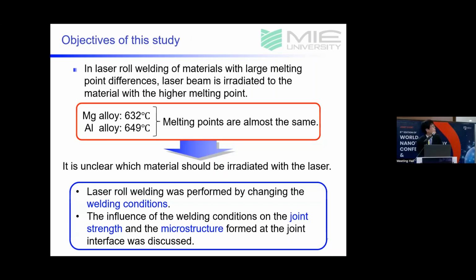In laser roll welding of materials with large melting point differences, the laser beam is irradiated to the material with the higher melting point. But the melting points of magnesium alloys and aluminum alloys are almost the same. In this case, it is unclear which material should be irradiated with a laser. Therefore, in the present work, laser roll welding was performed by changing the welding conditions, and the influence of the welding conditions on the joint strength and the microstructure formed at the joint interface was discussed.